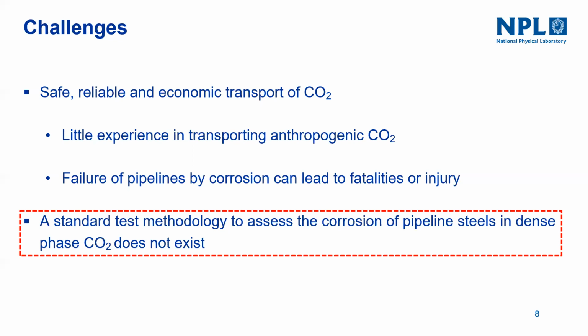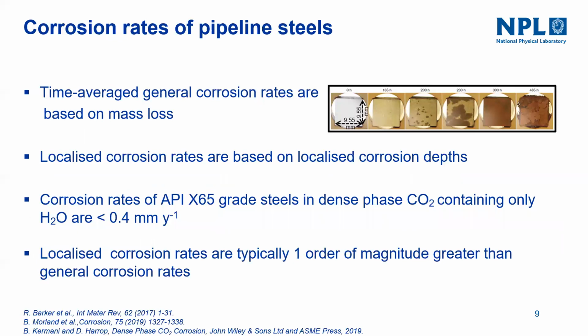For the successful deployment of CCS technology, we need to have confidence in the methodology of assessing the corrosion of pipeline steels in dense phase CO2. Before going further, I'll introduce how the corrosion rates are measured. One is time-averaged corrosion rates, where specimens are exposed to the dense phase CO2 and the mass loss is measured. The second is measuring localized corrosion rates.